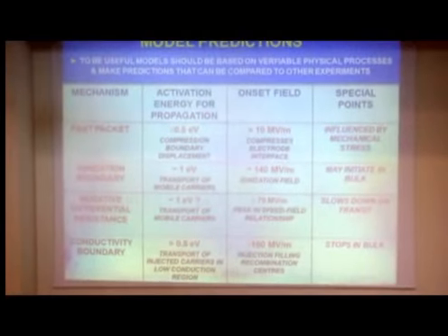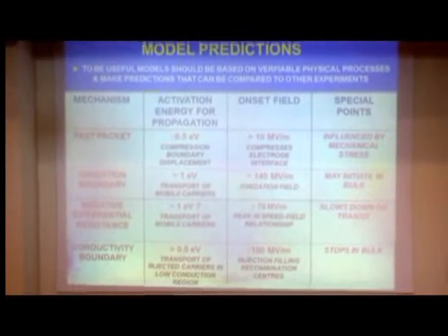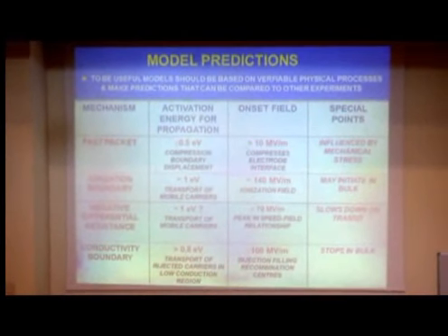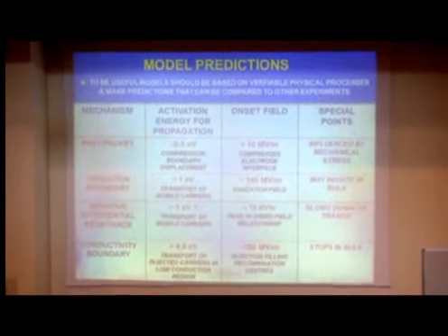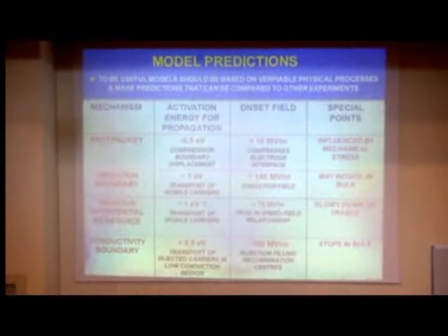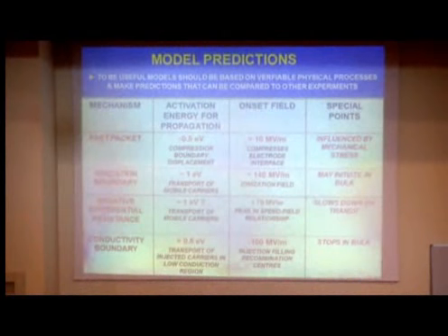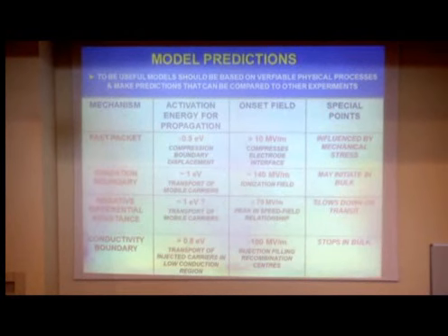Negative differential resistance should slow down on transit. And there are examples of this, but not every packet does this. The conductivity boundary stops in the bulk. This is a feature of the prediction. If your pulse doesn't stop in the bulk, it's not due to a conductivity boundary.